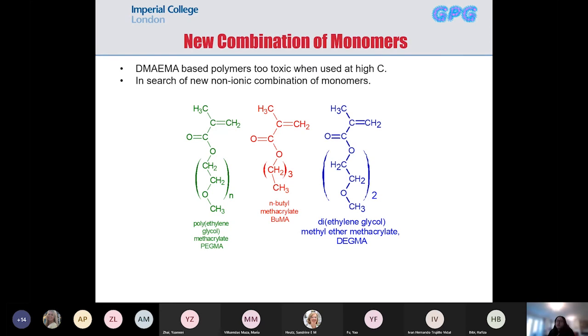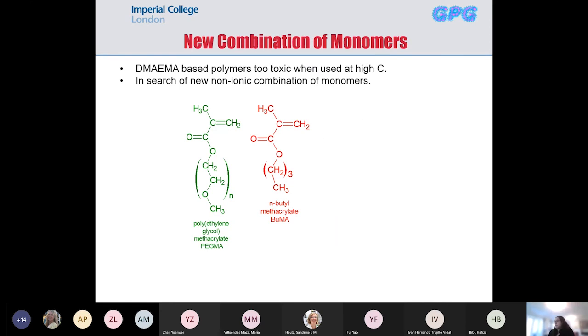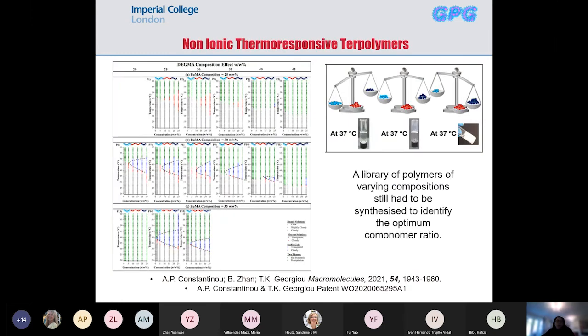And this actually showed us some exciting results. So it was a new chemistry. We knew that we were going to work in the ABC architecture with the B hydrophobic block in the middle. But we still had to vary the composition of the monomers to find the right composition to form thermogels. You can see some of them didn't form gels, and then we started having some gels, and then one of them was very, very good at forming gels even as low as 2 weight percentage. And that was one of the reasons that we patented this.